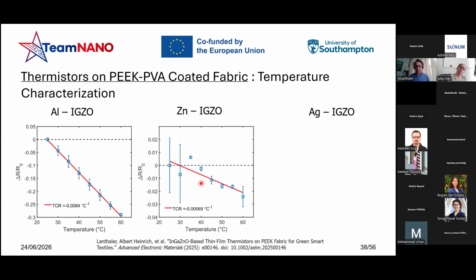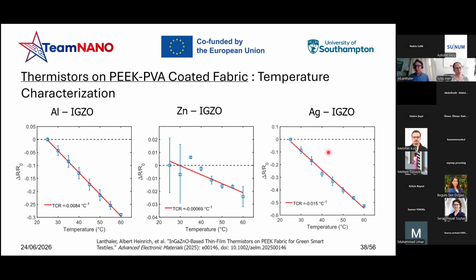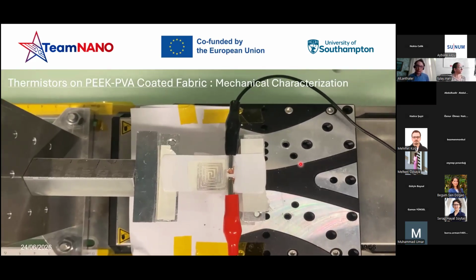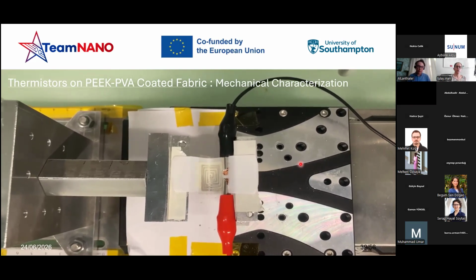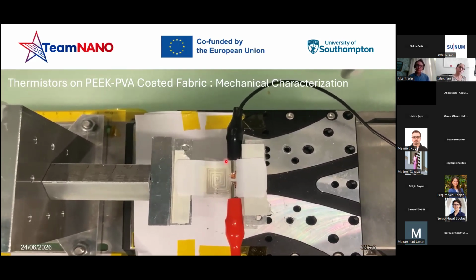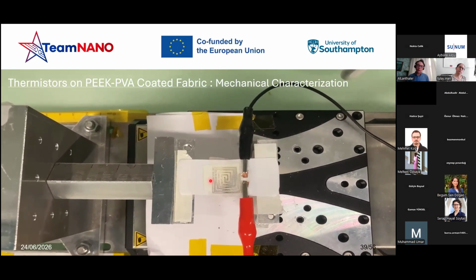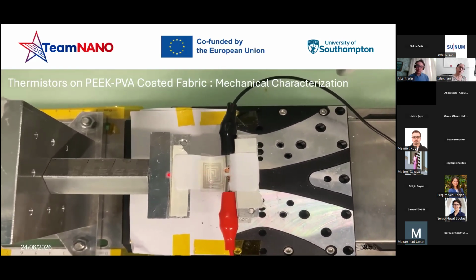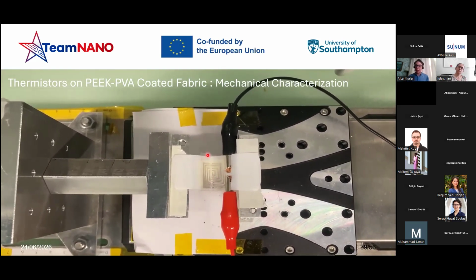For the zinc oxide, the situation was, of course, affected by the loss of contact. And last but not least, the silver one was more stable, precise, and accurate compared to the aluminum one, as mentioned before. After that, we tested it under mechanical conditions, dynamic mechanical bending, while measuring the resistance, completely in bend condition and in flat condition.